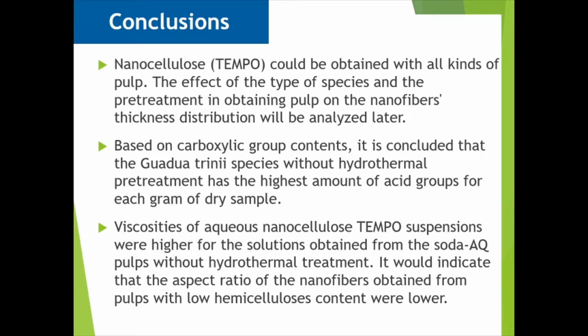Viscosities of aqueous nanocellulose TEMPO suspensions were higher for the solutions obtained from soda and anthraquinone pulps without hydrothermal treatment. It would indicate that the aspect ratio of the nanofibers obtained from pulps with low hemicellulose content was lower.